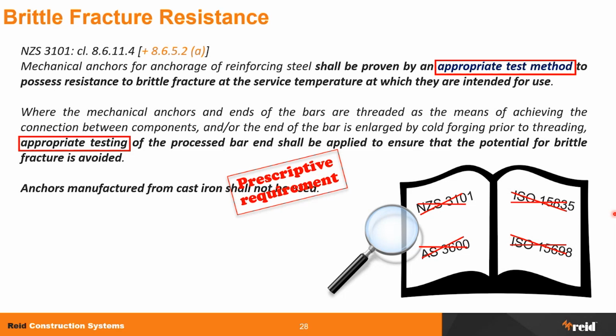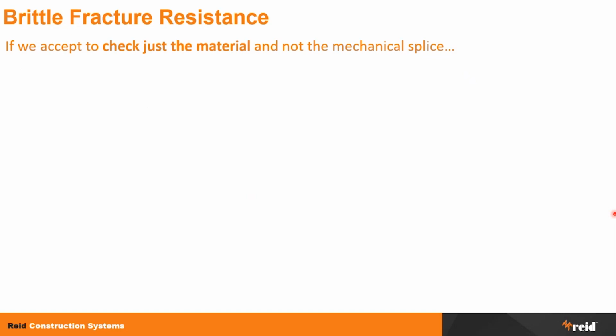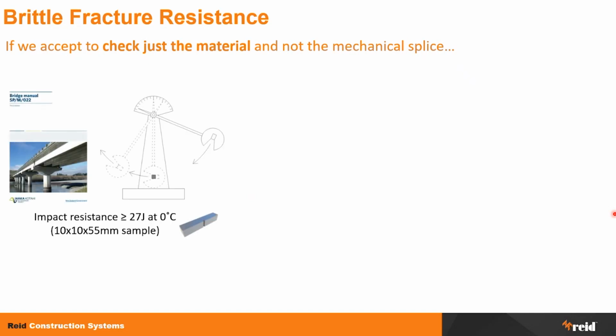They don't actually cover the testing against brittle fracture resistance of the couplers or fittings. So the point here is that if we accept to check just the material and not the mechanical splice as a whole, which would be more interesting, then the NZTA bridge manual advised to perform the Charpy V-notch impact test at 0 degrees.